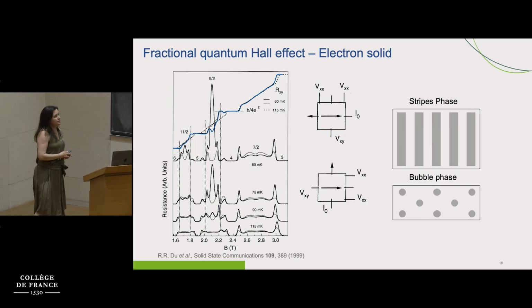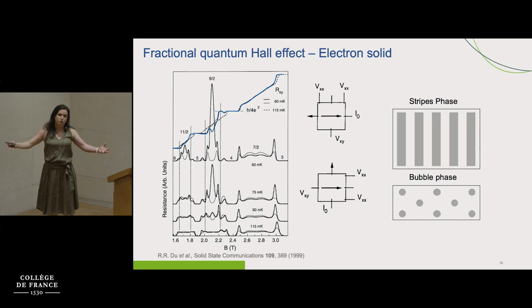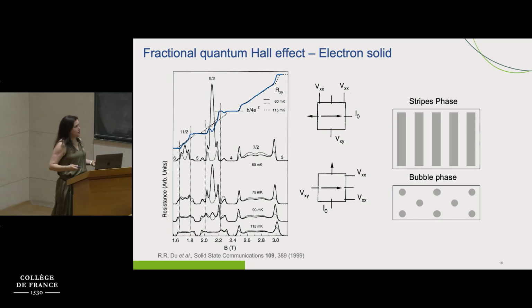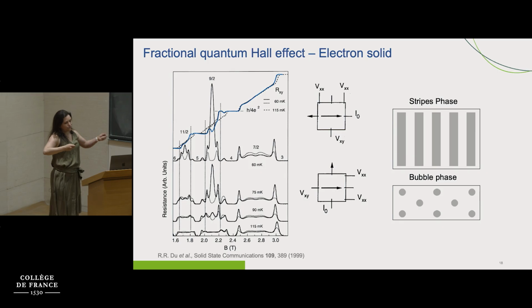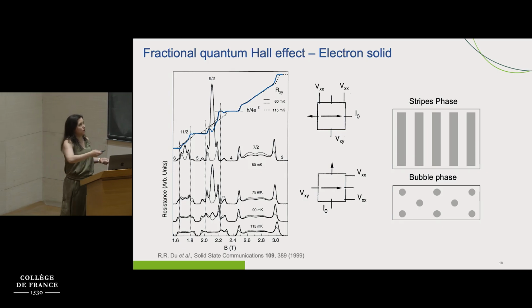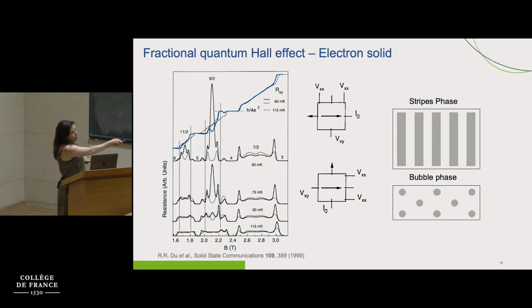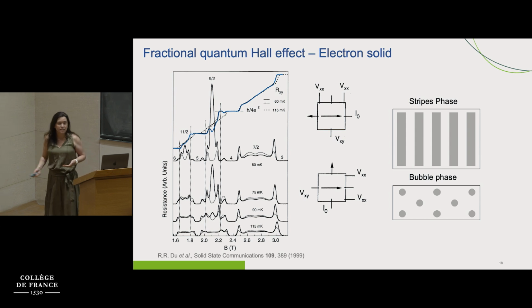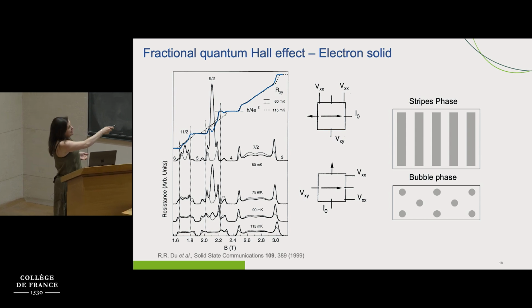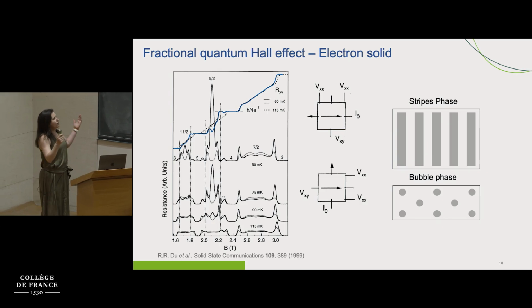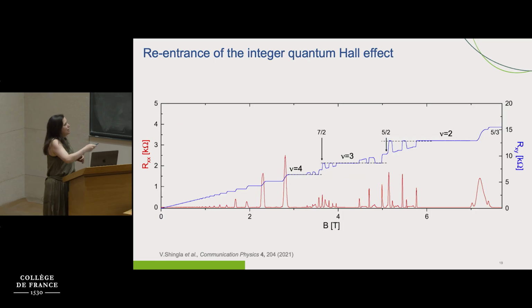So this has been associated with the formation of an electron solid, which means that the system, in order to decrease its energy, is going to arrange the electrons to form a solid. These solids can be either a bubble phase, which also includes a Wigner crystal, or a stripe phase. In this particular case, this is a stripe phase. That's why it's so anisotropic to measure passing the current in this direction or in this direction. A more up-to-date measurement of this can be seen here. This is still gallium arsenide.